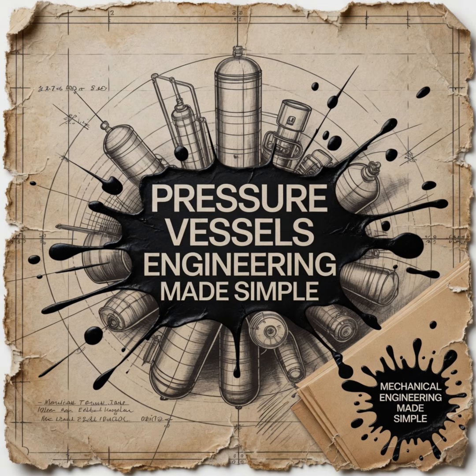The standard is hydrostatic, using water. Why water? Because water is practically incompressible. Meaning you can't squish it. Exactly. Its volume changes infinitesimally under pressure. When you pump a massive vessel full of water to 1,000 psi, the energy stored inside is relatively small. So if it breaks? If the worst happens, say a major weld seam splits open at peak test pressure, the water immediately expands by a fraction of a percent, the pressure drops to zero instantly, and the energy dissipates. There's no explosion. You get a loud bang, a split seam, and a very wet floor. It's a failure, but it's rarely a fatal disaster.